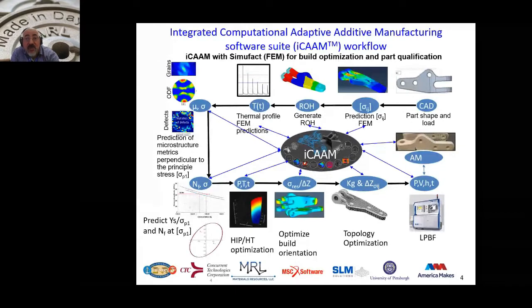We work with integration with SimuFact to identify the thermal profile using a hierarchical simulation that I will share with you later on. And from there, we call the iCAAM database and models to predict the microstructure as quantified by the two-point correlation, the orientation distribution function, and the defects. We have a quantification for it that takes into account the shape, the morphology, and the spatial distribution.